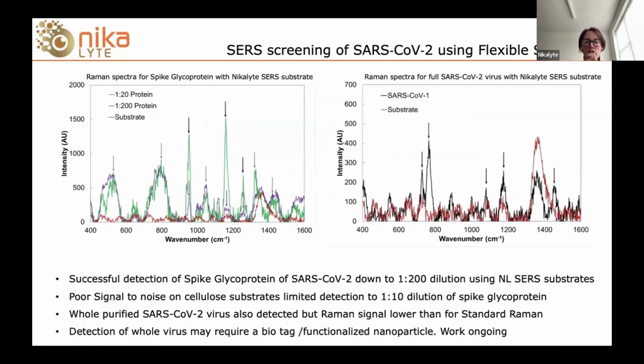So this graph shows the measurement data for the 2 different sets of experiments. On the left-hand side, we have the spike protein, the spike glycoprotein with Nikalyte SERS substrates. And you can see that he's looked at 1 to 20 and 1 to 200 protein dilution. And in both cases, we're seeing really clear peaks associated with that spike protein.